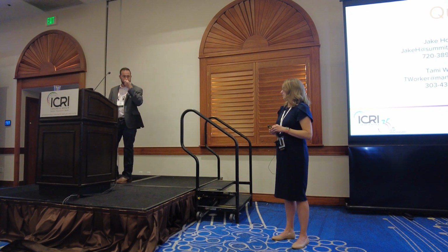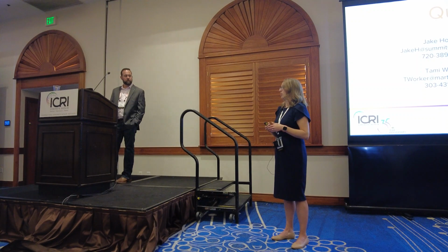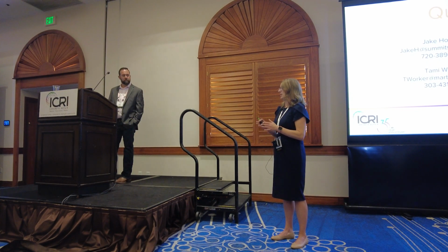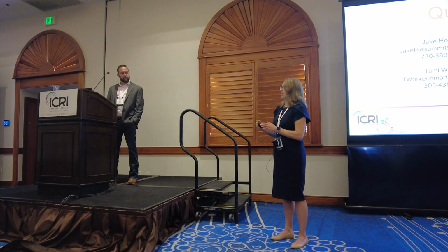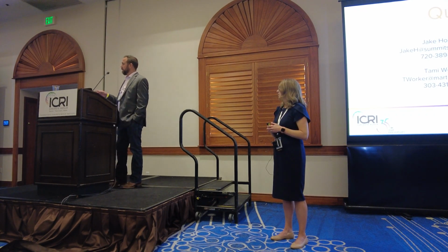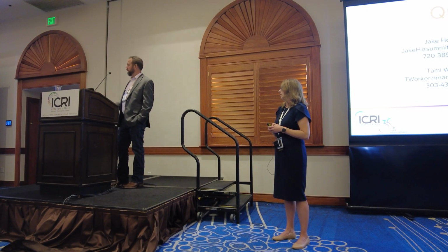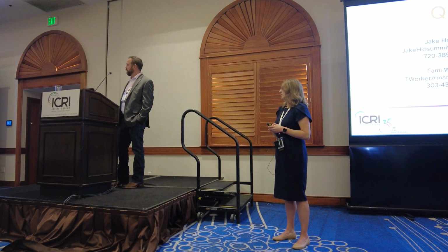So I don't believe that we did testing on the substrate in this particular case. This is something that's being worked through. I know it's clearly defined in ACI 562, which is adopted in some states but not in others. So I think that the industry is definitely moving towards where that will become a requirement on all drawings. We didn't have it in this particular case. We relied on pre-pour inspections and good surface prep prior to pour back. We did test the repair mortars as well, though. So at every repair location, we would do a separate pour off for that specifically. So we were testing both host and repair mortar.